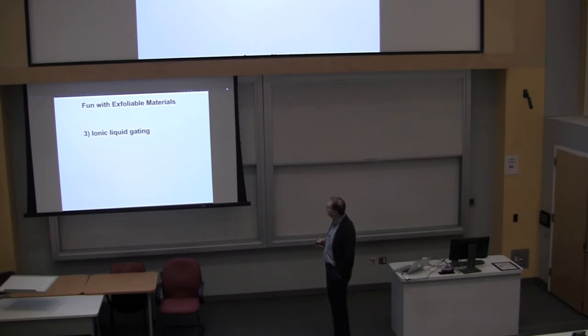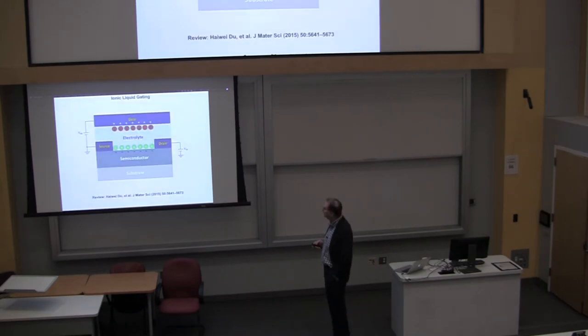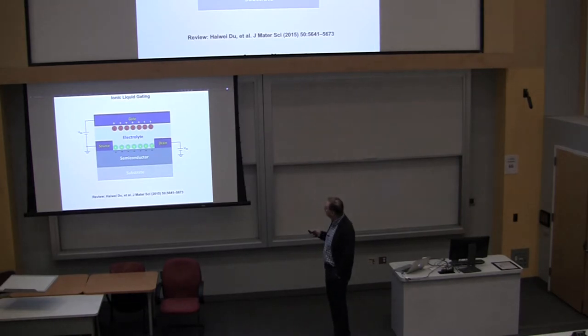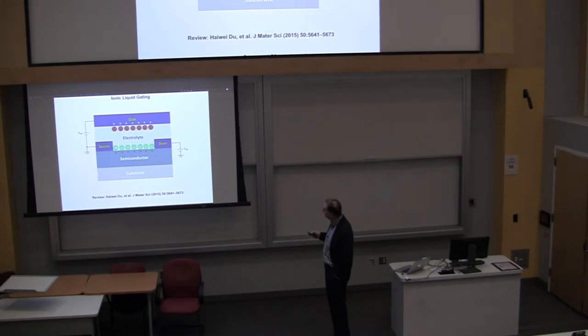So ionic liquid gating is another technique that you can use to do stuff with these materials. The basic idea behind ionic liquid gating is you have an electrolyte, which is an ionic liquid. It has positive and negative ions in the liquid. And the idea is that if you put a drop of liquid on your sample, so here's a semiconductor, here's a drop of liquid, you have a source, a drain, and a gate. So you put a gate voltage on, you drive the ions in the liquid, so you say you lay down the positive ions on top of your sample, negative ions near the gate here. So if you have all these positive ions sitting on top of your sample, you're going to attract electrons, and you can create a 2D electron gas at the surface of your semiconductor. That's the idea. Now, this cartoon, it turns out, isn't very good.